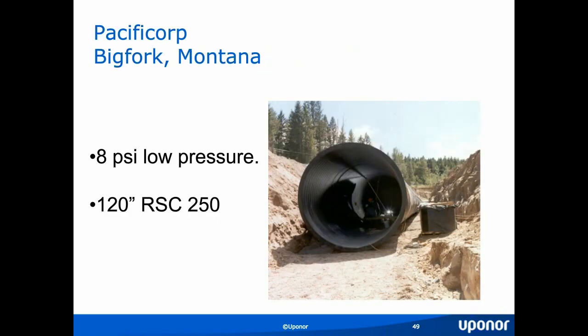You can see the front end of the pipe just as it's being welded together and under construction for the Pacificorp job. This particular pipe was 120 inch with a ring stiffness coefficient of 250. The ring stiffness coefficient is the particular stiffness of the pipe, and it's that parameter that you enter into our web calculator to determine the loadings on the pipe. And it also, the ring stiffness, tells you what sort of pressure that this particular pipe will withstand. Being at 8 psi, we had to do both an ID and OD weld on this pipe, as the internal welder that we normally would have used was not built or designed yet.